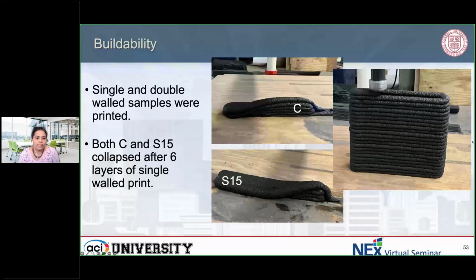And you can also see that there's a lot of variables that go in here as well. It's the layer height and where your extrusion nozzle is as you are depositing the material. That will also affect your bond strength between the material systems. And this one specifically has very good buildability because the shape of your layer is not becoming like a pancake, it's not getting smushed as you're placing more layers. It's able to hold on to its shape. You also don't have excessive tearing as your material is being placed.